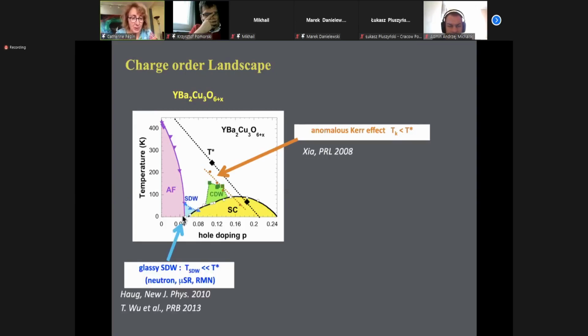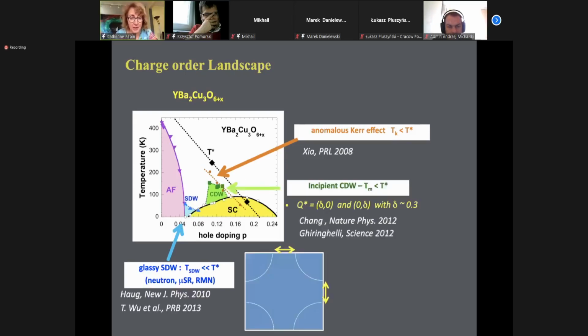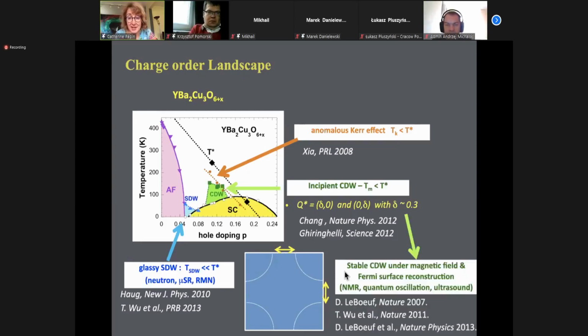Here at low doping, you have glassy behavior. You have what I'd call incipient charge modulations below T star in most of the compounds. We know that the wave vector is very close to the nesting wave vector of the antinodal region. And we know we can stabilize it with magnetic field, which is very unusual. Under magnetic field it gives a true long range order, with almost no disorder and very nice Bragg peaks.